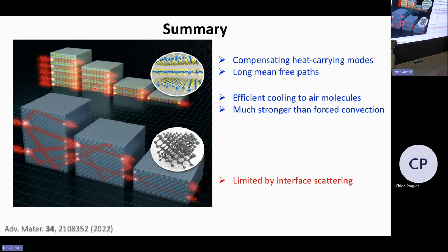Now in silicon, the situation is very different. It's a 3D bonded material. So you have phonons going in all directions. And when you make it thinner and thinner, they're going to interact more and more at the surface. So you get scattering at the interface that starts dominating and limiting your thermal conductivity. Now, an additional fact that's likely happening is that the surface roughness in a 3D material is much worse than, of course, in a 2D material. So there could be an additional effect that the surface roughness gives even more scattering when you thin down your sample more and more.